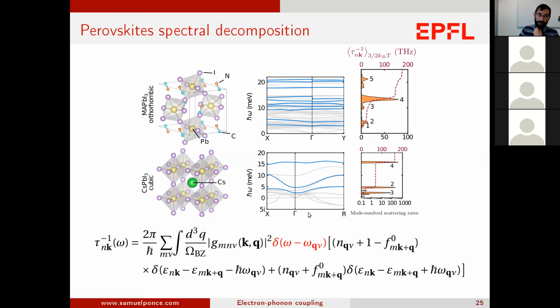Here what I'm showing is the spectral decomposition. It is simply the scattering rate, but now I have introduced a Dirac delta with the phonon frequency. So what you're seeing here is the contribution to the electron-phonon coupling for a given phonon frequency. The dashed line is the integrated one, such that when you integrate over all frequencies, you recover the total scattering rate. What you can see, both for MAPI and cesium lead iodide, is that you have no contribution from acoustic modes. It's all optical modes that contribute.